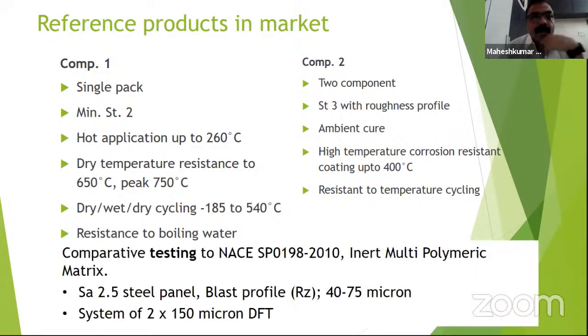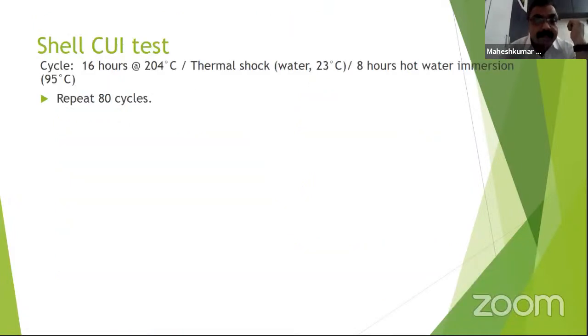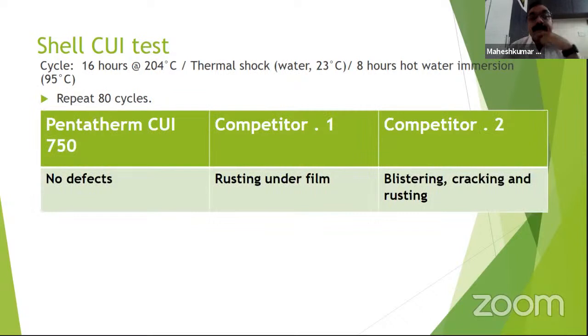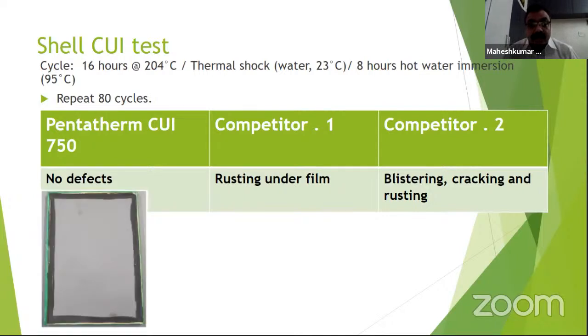So we applied those panels as an inert matrix coating onto various substrates, and we also carried out the Shell CUI test. When we had done it, we found absolutely no defects in the film as far as the exposure is concerned. Exposure was 16 hours at 204 degrees centigrade max, thermal shocks at 23 degrees centigrade, and then again a hot water immersion at 95 degrees C.